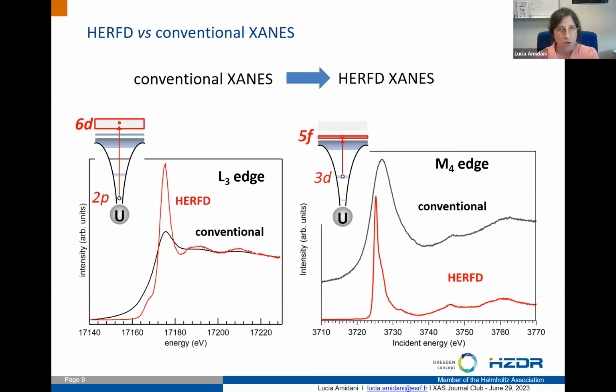And we use an X-ray spectrometer. Why? Because in the case of actinides, the increase in resolution we can gain is really huge. Here I'm plotting an example of what changes when we go for conventional versus HERFD XANES at the L3 edge and at the M4 edge. As you see, we gain visibility of structures that would otherwise be hidden, and this is particularly true for the M4 edge. This is why M edges in general are typically measured nowadays only with HERFD spectroscopy.